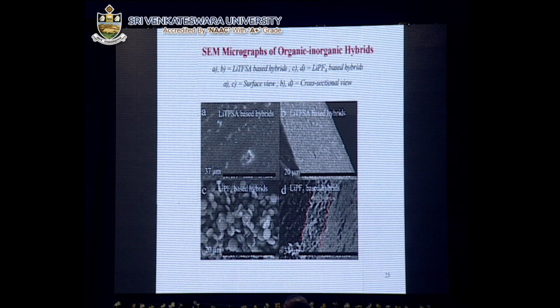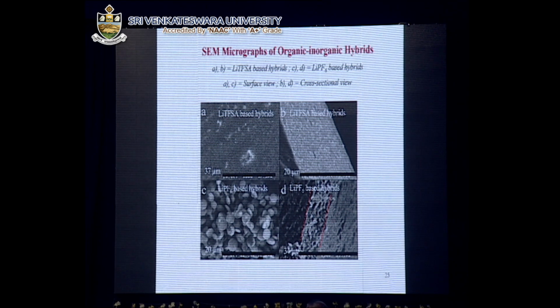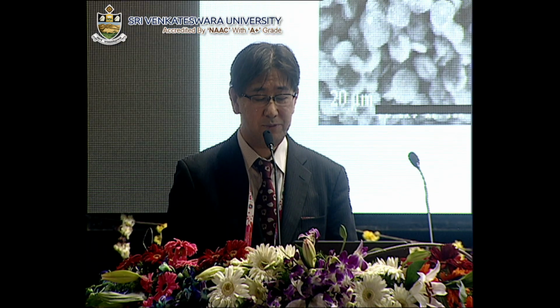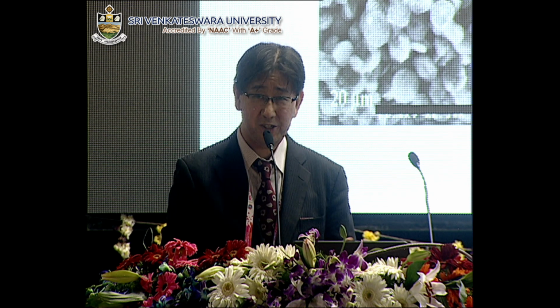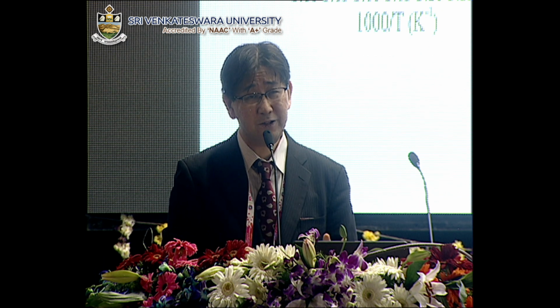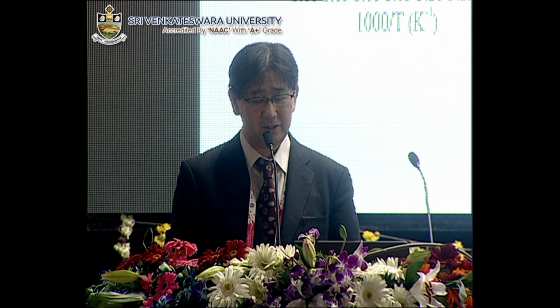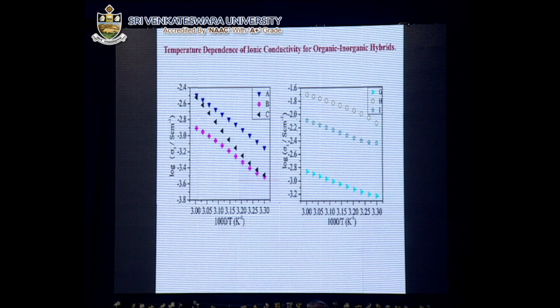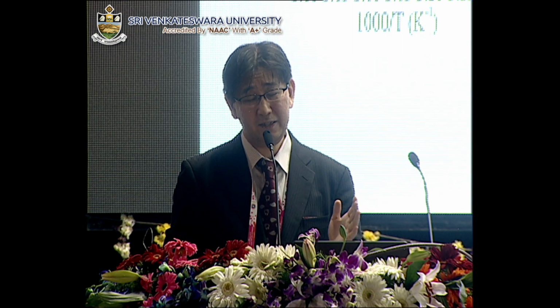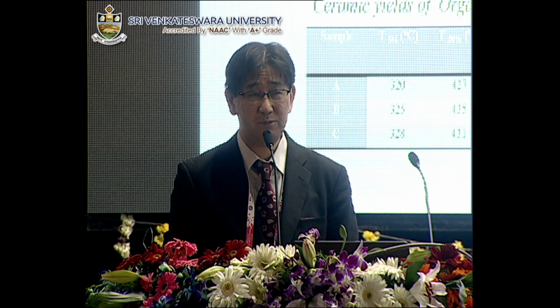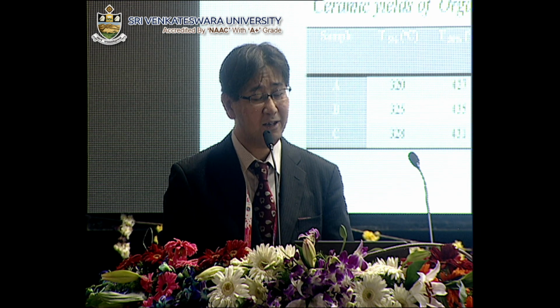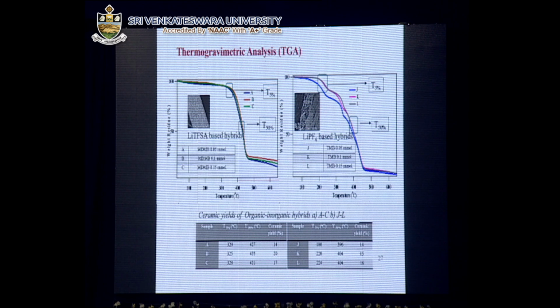And the SEM image shows that the lithium TFSI based system showed a fairly homogeneous texture, showing very small phase separation order. On the other hand, the lithium PF6 based system showed discoidal profiles, indicating a higher order of phase separation. And such a morphological difference had largely affected both the ion conductive behavior and the thermal behavior. For instance, in the case of lithium PF6 based systems, a fairly high ionic conductivity was observed, possibly due to better connection of ion conductive paths and a higher order of phase separation. On the other hand, in terms of thermal stability, the TFSA based system showed a much higher thermal stability, indicating that homogeneous mixing of organic and inorganic moieties is highly important in achieving such high thermal stabilities.